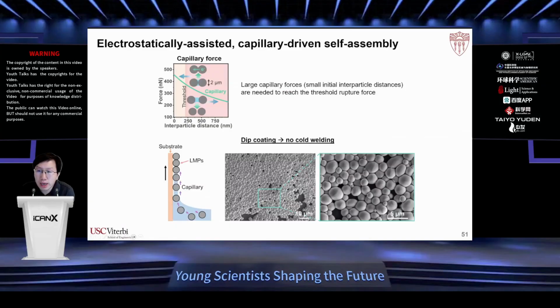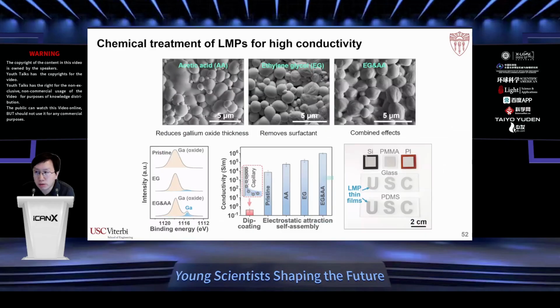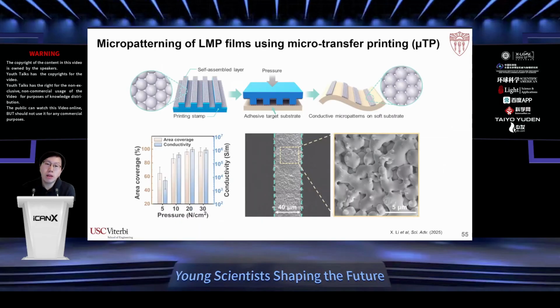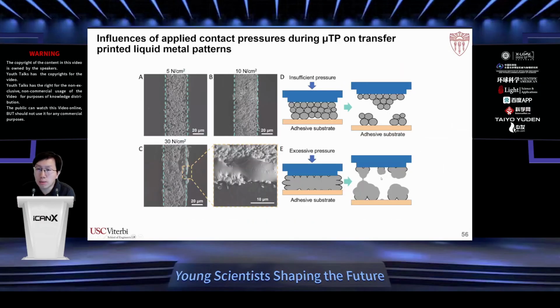And the key is that if you do just the dip coating, you are not able to form a conductive pathway because of the insufficient surface tension. So I'm going to skip these. And then we combine this self-assembly process with transfer printing, which allows us to pattern this self-assembly layer at micro scale, because we can do lithography using the stamp. So this allows us to form micro scale patterns.